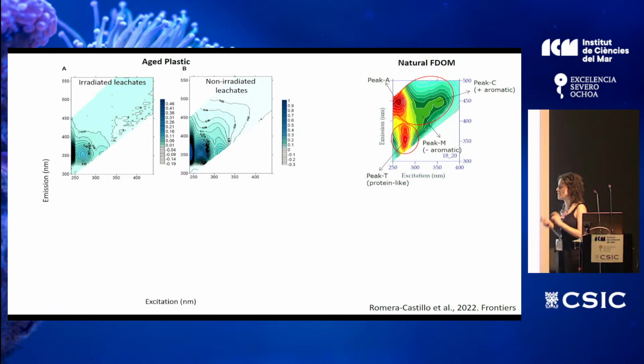And here we have the result of the leachate of both. This is only the aged plastic, because in the new plastic, or the LDPE, we didn't find any clear peaks of fluorescence. So here are the fluorescence matrices. I have left here the natural DOM fluorescence matrix just to compare, but these are the ones from the experiments. These are from the leachate generated in irradiated condition and those generated in non-irradiated. In both, you can see that the plastic releases substances fluorescing in this area, which is the area where the protein-like substances fluoresce in natural DOM. Of course, these substances from the plastic are not proteins, but other substances fluorescing in the same area as proteins. That could be, for example, polyaromatic hydrocarbons or phenols or others.